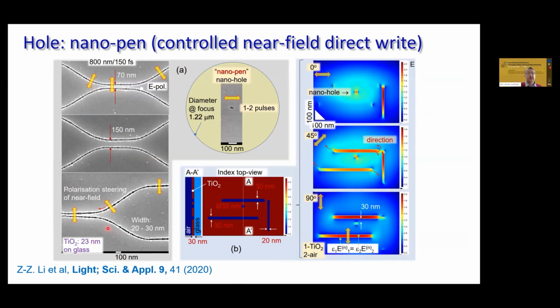So this is on the left side. This is really unusual. If you even consider electron beam lithography, it will be very challenging, without any change of conditions, to write patterns in close proximity without changing exposure dose. And here it just comes for granted. You can write and modify nanogrooves on the surface of titania, your resist in this case, just without any complication.